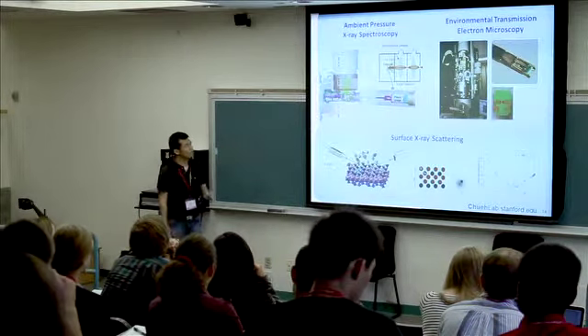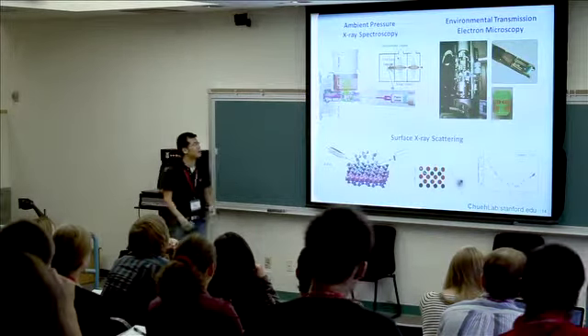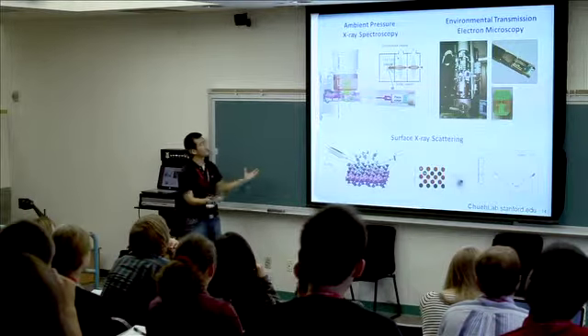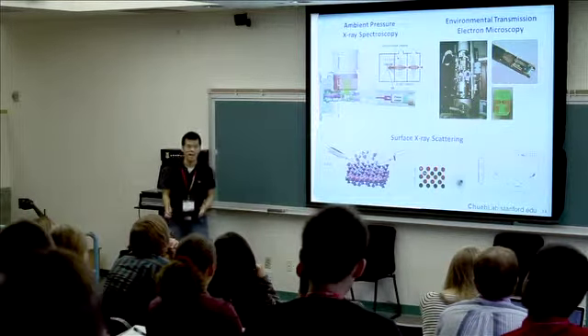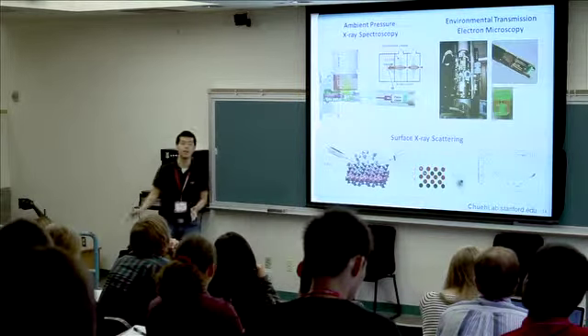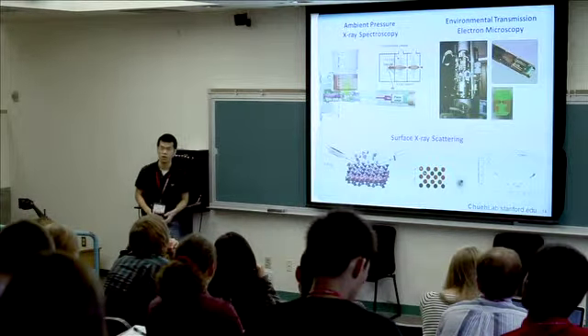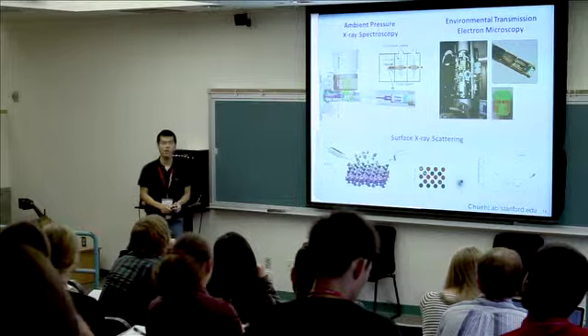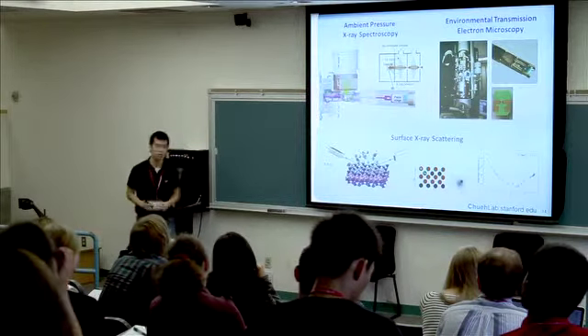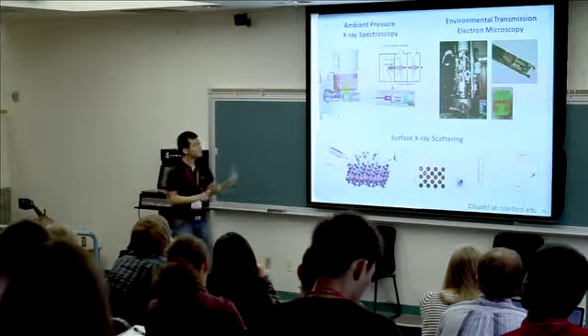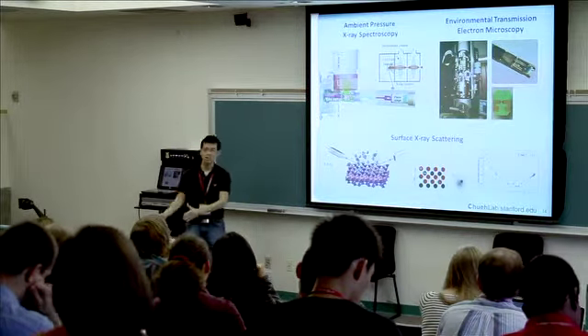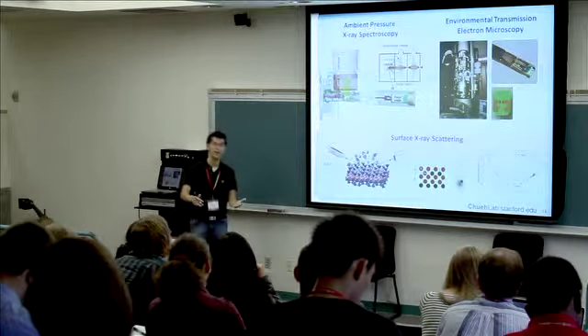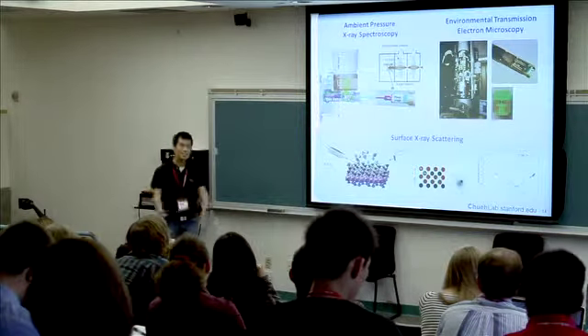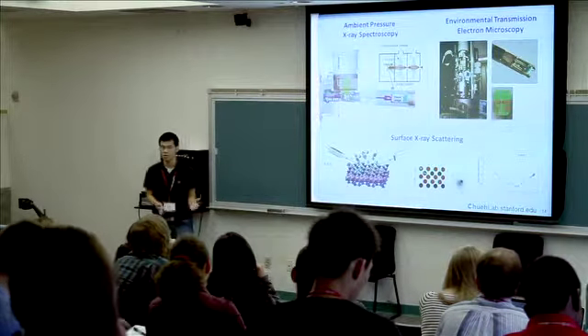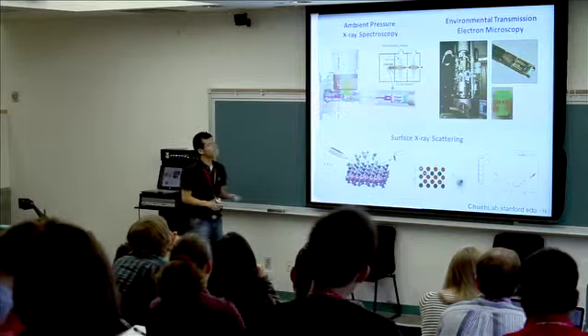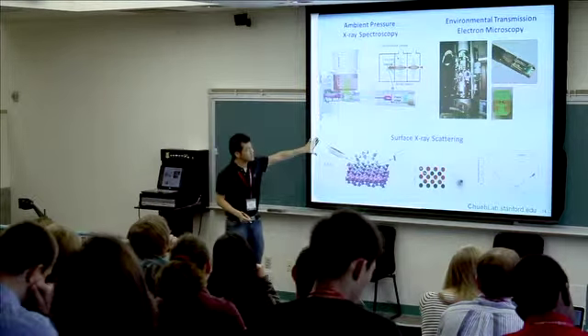But along with scientists at SLAC and at Lawrence Berkeley National Lab, we're now developing special apparatus that can operate at pressure as high as 100 torr. That's higher than 1/10 of an atmosphere. So we have essentially a 10 order of magnitude increase in the operating pressure of spectroscopy techniques. This is very interesting because now we can put in the hydrogen, the water, the methane, and we can see what happens to the electronic structure of the surface as the reactions take place. The second technique that we're applying is called surface X-ray scattering.